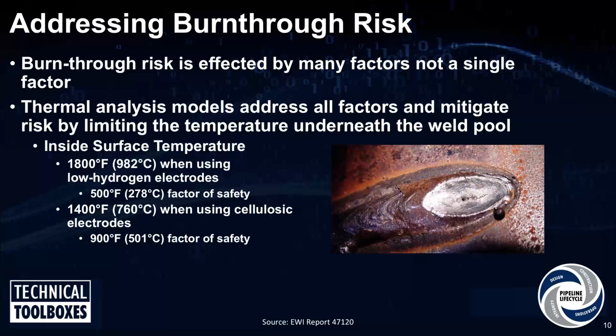So these 1800 F and 1400 F limits that the PRCI model uses have a built-in factor of safety relative to the actual temperature of the pipe wall of actual burn-throughs of 2300 degrees. So if you run these models and your inside surface temperature is 1805, are you going to burn through at 1805? No, not really. But again, you just have to understand you're reducing some of the factor of safety. Now, I don't know why the engineers picked 500 degrees or 900 degrees, but that's what they did to add that factor of safety.